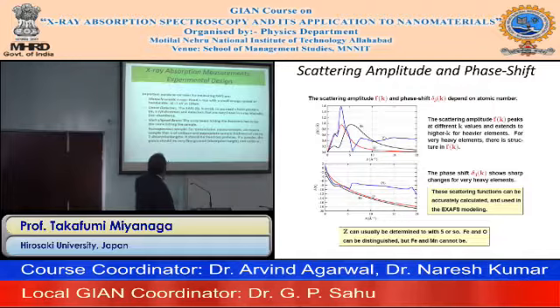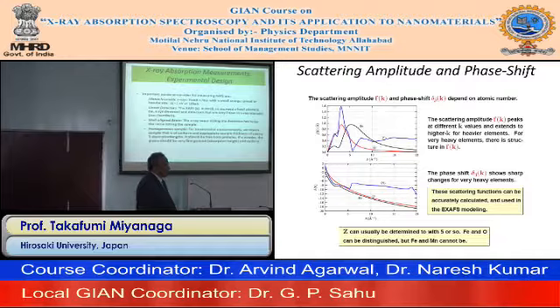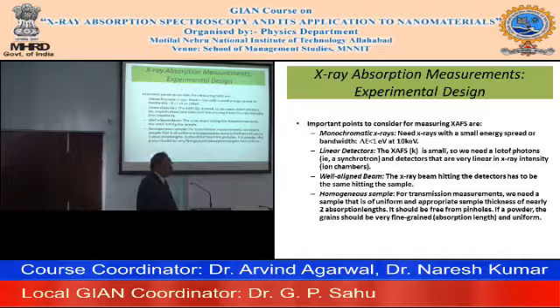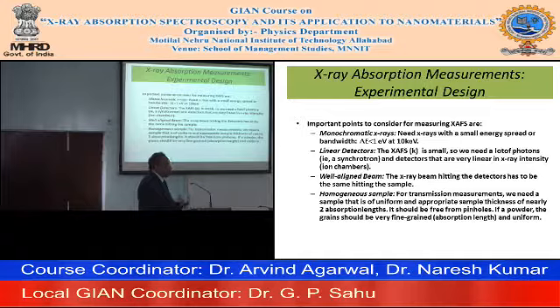These are the important features associated with X-ray absorption experimental design. In our lab we used the bent crystal spectrograph and traditional X-ray units, which give out very low intensity, and photographic film for recording data. Nowadays, monochromators, EXAFS detectors, and well-aligned beams are used. One important thing: the sample should be homogeneous; otherwise the intensity varies and the thickness varies, which distorts the EXAFS structure.